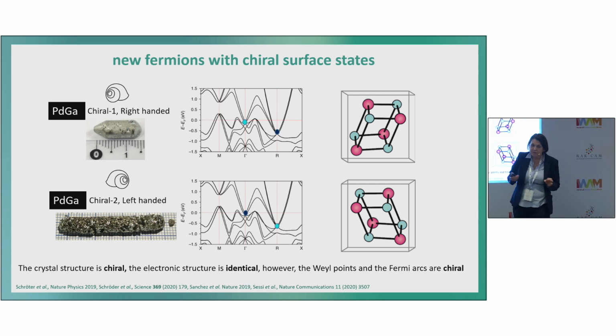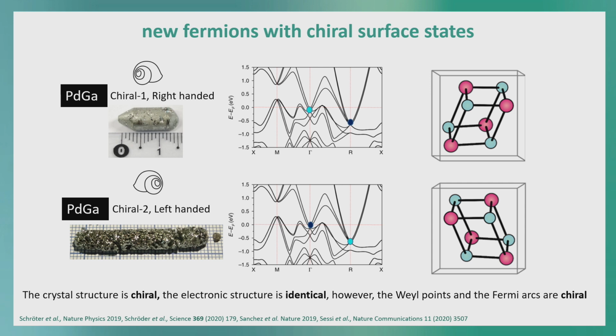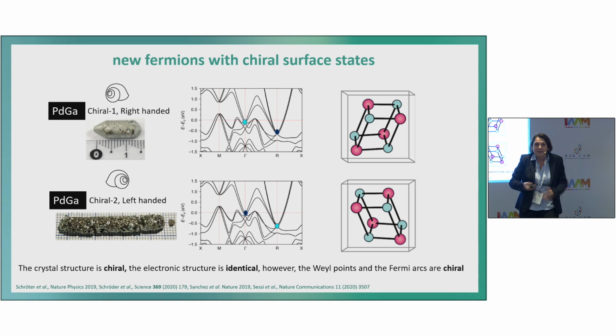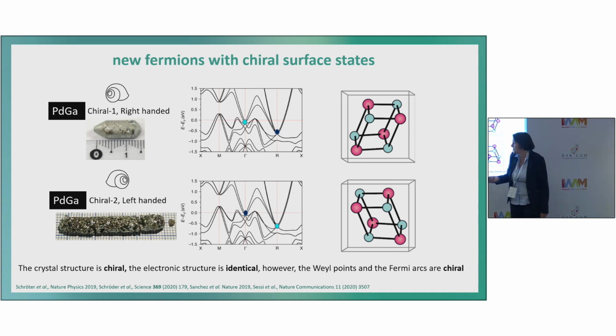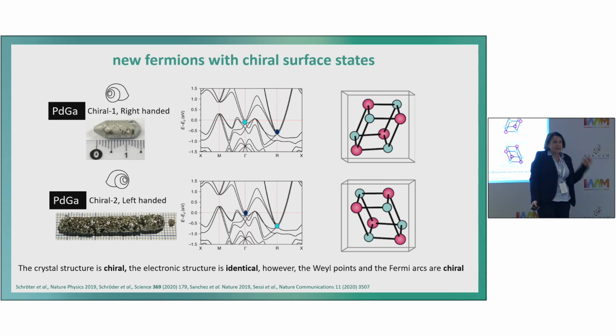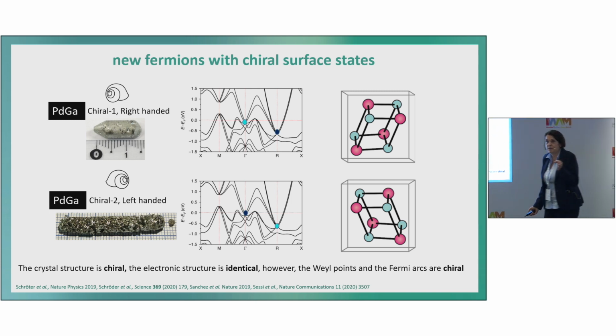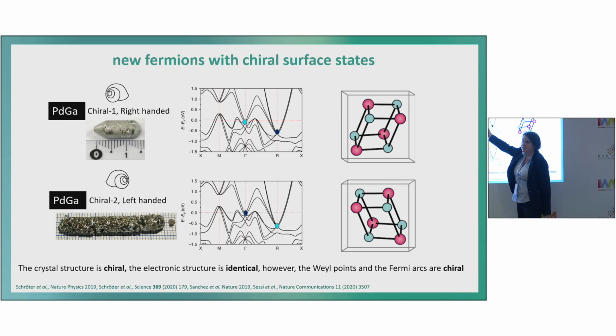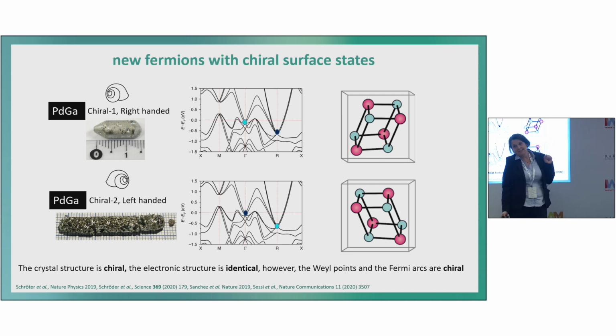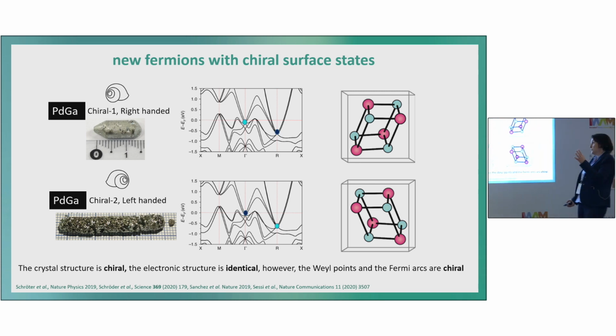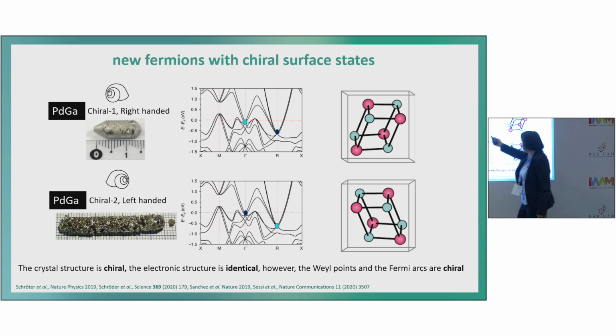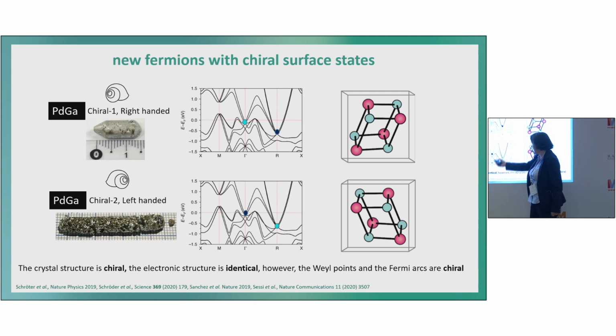The interesting thing is both chiral crystals have the same band structure, and this is the whole trouble why we cannot separate one enantiomer of a molecule from the other enantiomer, because the electronic structure is totally the same. If you draw your molecular orbital diagram for one molecule, it's just the same as the other one. So the band structure is exactly the same. But if we have topology, there's a small difference, because if we look at the chirality of the Weyl points, here we have the two Weyl points at different energy, and the chirality of the two Weyl points is different. So we can distinguish the two crystals by this, I have to prove it, but first of all, it's the case. So you see this is a light blue chirality, and this is a dark blue, and here it's vice versa.